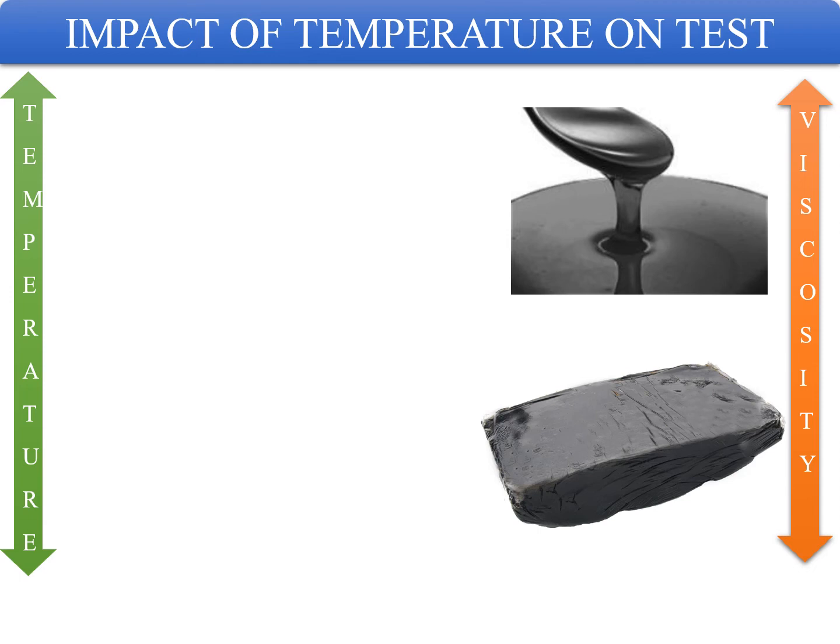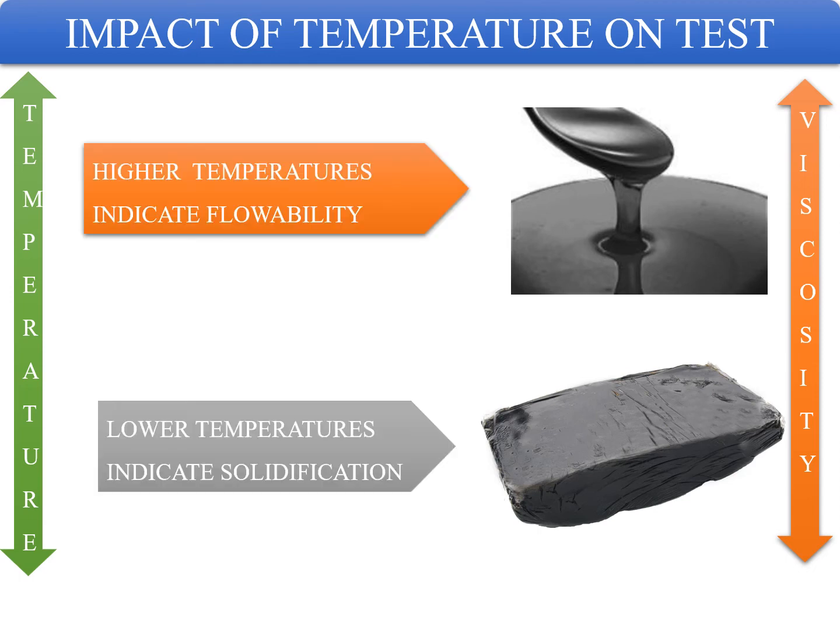That means if you have a 30-40 grade of bitumen, and you heat it by mistake for a longer duration of time, then the penetration being tested at 25 plus minus 1 degree centigrade will show a result which will be misleading in nature. It might show that the bitumen is being penetrated more than the 30-40 range. It might be possible that your sample will get a penetration value more than 60.